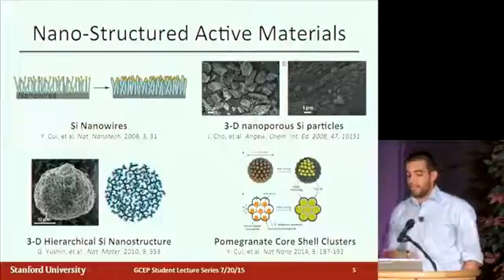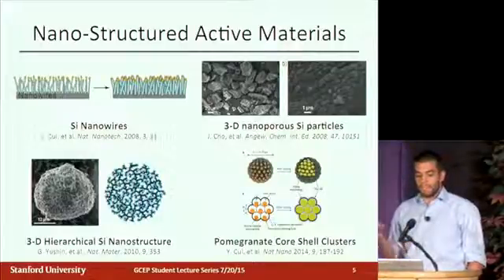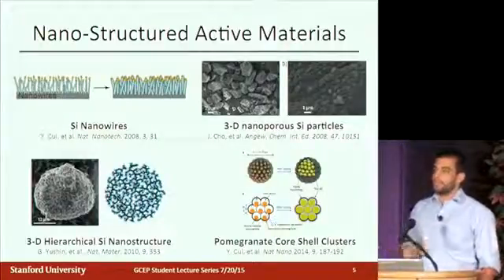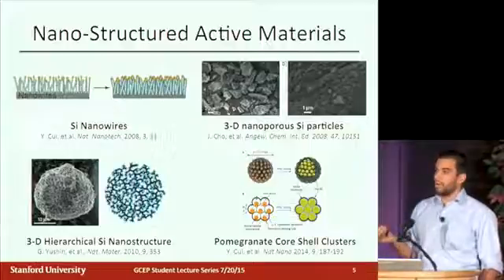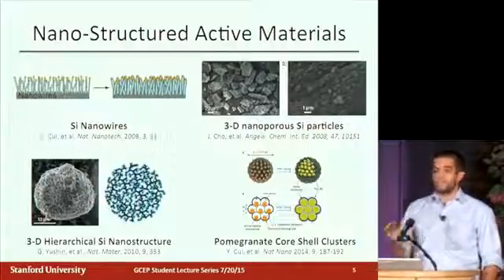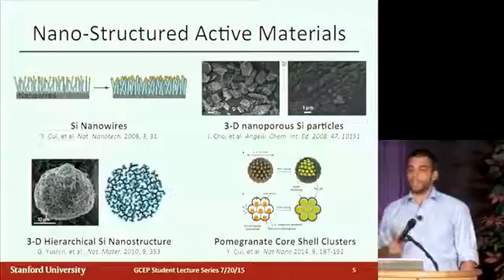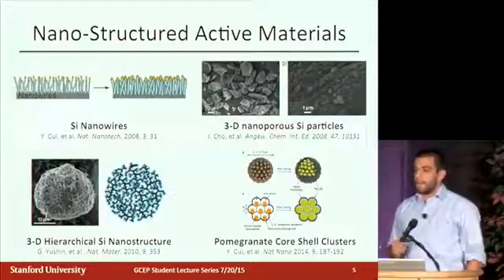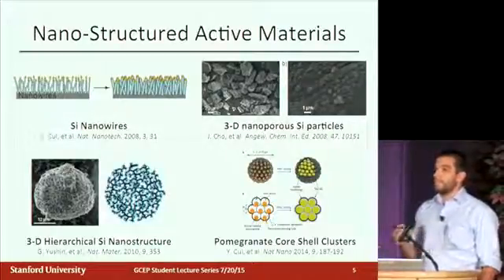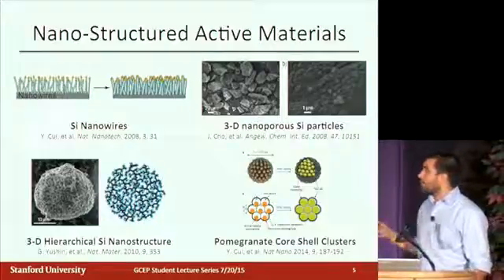One of the approaches, one of the most widely used ones, and a really exciting one, is to do nanostructuring. If you structure the silicon below about 150 nanometers, that's really the critical dimension they found, it stops breaking, and so it'll just expand and contract anisotropically along different crystal planes, but it won't fail. And so there have been numerous ways.